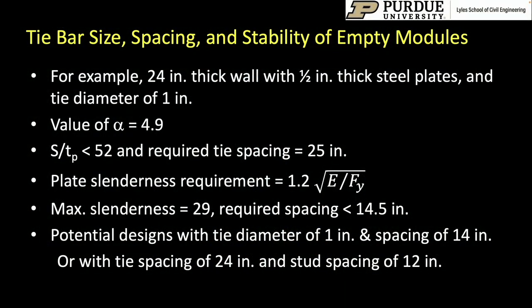And together, these two pieces of information provide us with pretty much all the information we need in order to detail the system. What should be the diameter of the tie bars? What should be their spacing? If shear studs are used, they're only going to work after the concrete hardens. The shear studs cannot help you while there is no concrete in the system. So you can add shear studs, but they'll only help you after the concrete has hardened. Tie bars will provide support both before the concrete hardens and after it as well.